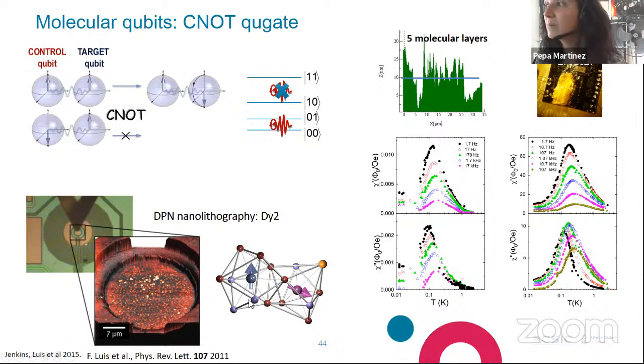To demonstrate that these spins are not collinear, what we did was to compare the equilibrium magnetic susceptibility. This is not equilibrium susceptibility; this was measured at different frequencies. But if you plot the equilibrium magnetic susceptibility against temperature, you see clearly the different regimes, which you can ascribe, for instance, to the system being thermally activated, to the system being antiferromagnetically coupled between them, or even reaching dipolar order between all particles. Okay, but yes, sure, these measurements do not tell you that this is happening.